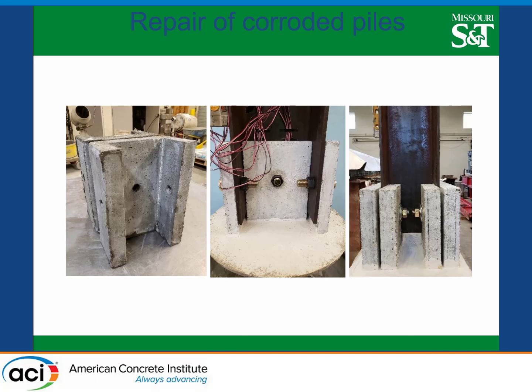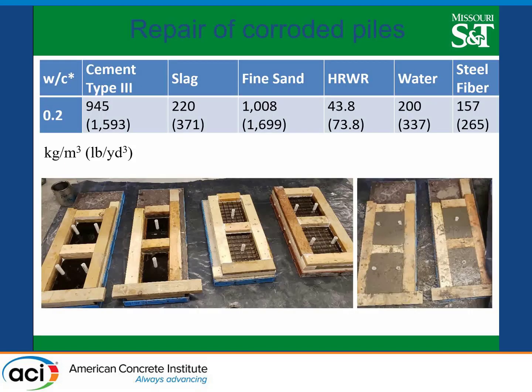We look at different thicknesses, starting from 1.5 inch all the way to 3 inches. One of the limitations over here is looking for something practical. They would like something that can be easily carried by a maximum of 2 workers. So the weight was really one of our big concerns for these plates, and this is why we try to reduce the thickness. And reinforcement. For these UHPC, they don't want to use any over-the-counter mix. So we try to develop a mix using our locally available material. This is the best that we can come up with.